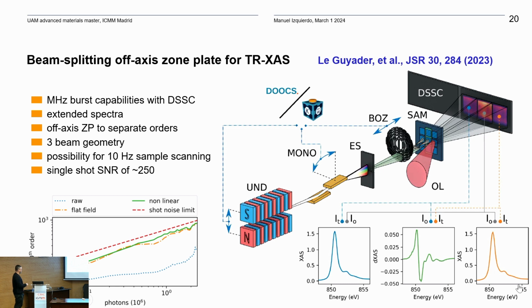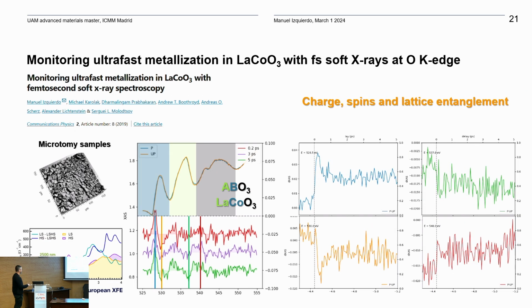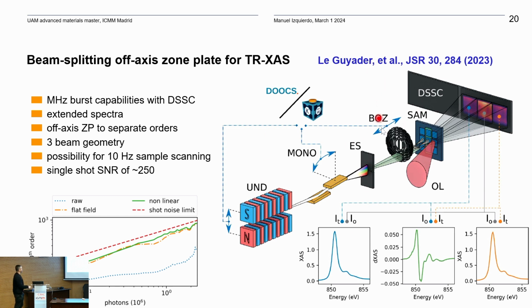So in order to do this, what we have here is this beam splitting off-axis zone plate. This is a combination of a diffraction grating and also a focusing zone plate. When the monochromatic FEL impinges on it, it will separate into 3 diffraction orders, 0, +1 and -1, and it will focus a little bit before the sample, and then you illuminate the sample that is here on a membrane. Normally the substrate is silicon nitride, and then the outgoing beam will propagate 5.2 meters, and then it will impinge on the DSSC detector, producing this kind of images.